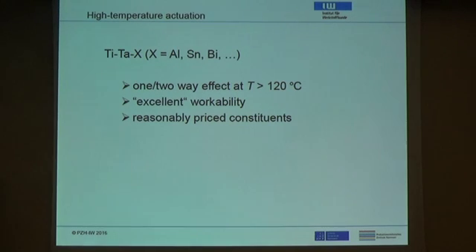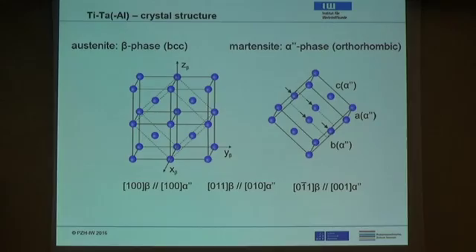Okay, so for high temperature actuation, we choose titanium tantalum with some ternary elements like aluminum. And it's well known that this material does show a one-way and a two-way shape memory effect beyond 120 degrees C. It is fairly good to work. Basically, it's titanium, and the constituents in there are reasonably priced, I would say. So this looks like a good material.